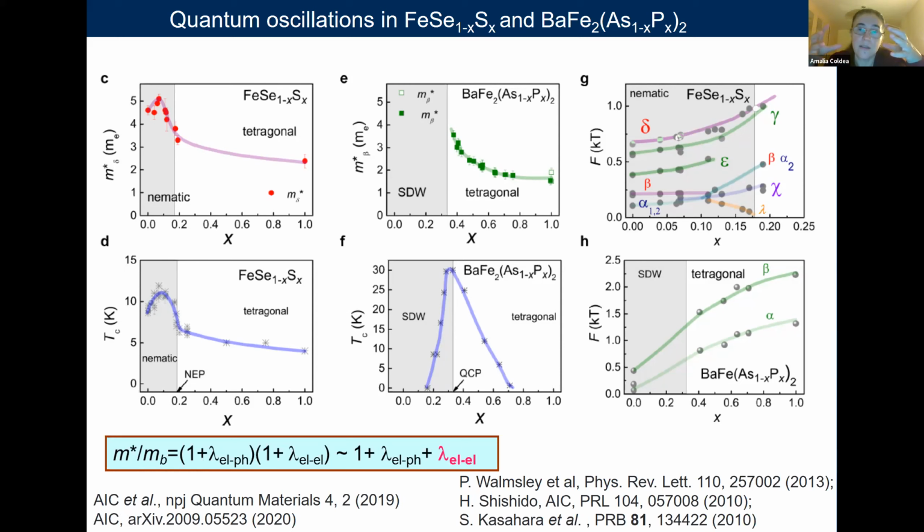If that area is slightly distorted, or if it's completely isotropic, it's still an area. Especially in the vicinity of the nematic endpoint, we know from ARPES that these areas become more and more isotropic. So because quantum oscillation probes an area, it is not affected by other parameters. It's the cross-section area of a Fermi surface and the quasi-particle cyclotron average quantity for that particular pocket.